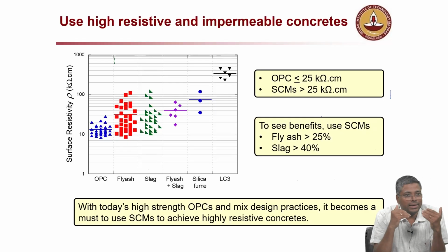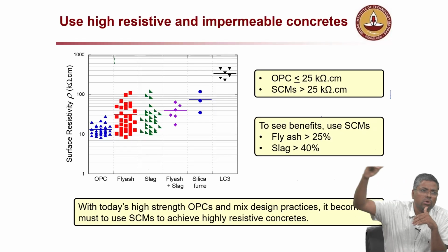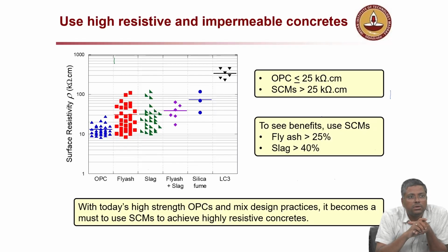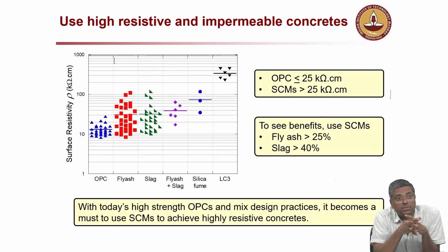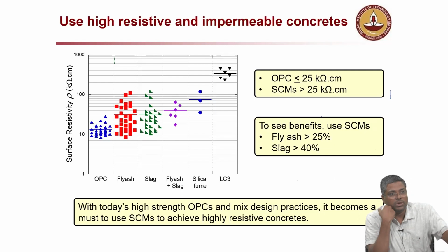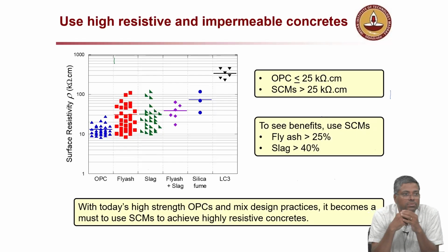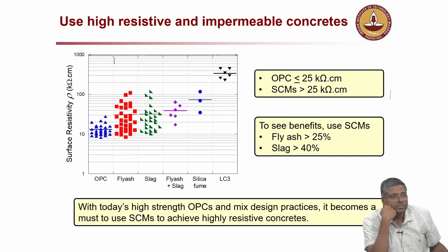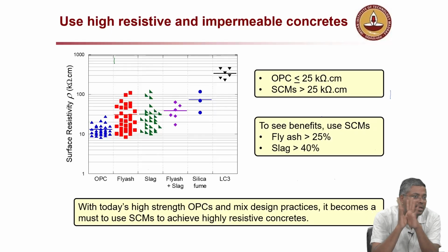Okay. So if I need high performance concrete, better to go with more and more fly ash or slag. If you put too much, maybe, and if you don't cure very well. Okay. Probably Manu might have talked about it, the pozzolanic materials, right? The pozzolanic reaction is very, very important, for which you need to have calcium hydroxide from the OPC system that has to react, and then you will get more CSH in the same volume. So if you put too much of fly ash, then I mean there are systems where high volume fly ash with 90% and all that is there, but then you need to properly cure. A lot of additional effort is required to achieve the real behavior. Okay, for all practical purposes, I would say go with somewhere in this, the second box on the right side. If you follow, you will really get good quality concrete.